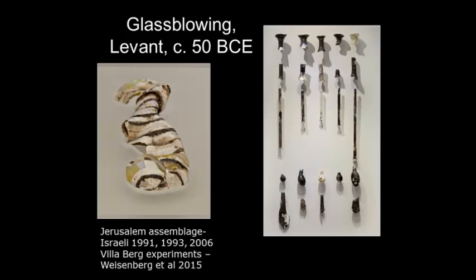It appears to have been blown from materials like this — the accompanying debris includes glass rods, hollow glass rods. The glass vessels appear to have been shaped by blowing down preformed glass rods. They heated the end of the rod, fused it, and then blew. And for the first time, or one of the first times, they started blowing glass vessels. Recent experiments by a German group have shown that this can be quite a practical method.